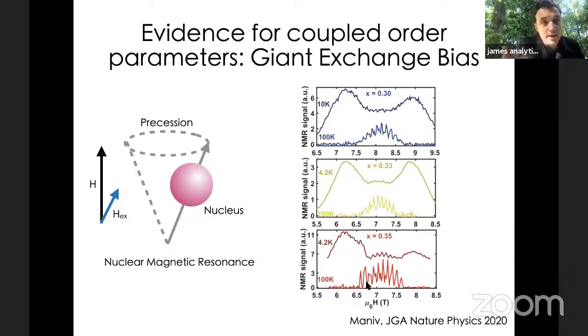And in all intercalations, you get a very well-defined nuclear moment. In other words, it seems that the moment that we detect has a very similar environment in all of the intercalations. And otherwise, what you'd normally see if there's multiple environments is that you would see multiple splittings, is my understanding, from the same moment. Whereas we see basically the same environment, no matter what the intercalation is.